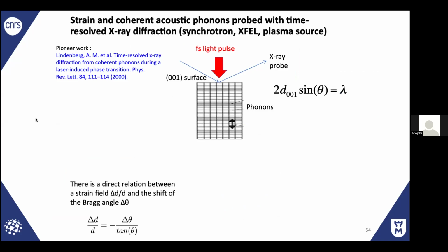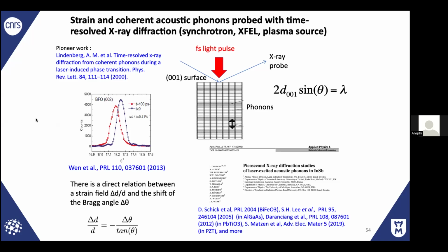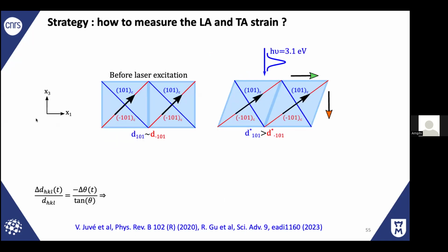To do that, it's important to make X-ray diffraction, because with X-ray diffraction, you can have direct access to the strain, which is the relative variation of the interatomic distance over the equilibrium distance. And of course, as you probably know, this is the Bragg law. People apply this Bragg law for time-domain diffraction. In that case, you use a femtosecond light pulse that induces different phonons, and by using X-ray diffraction, you look at how the Bragg peak shifts, then you measure that variation and come back to the strain.